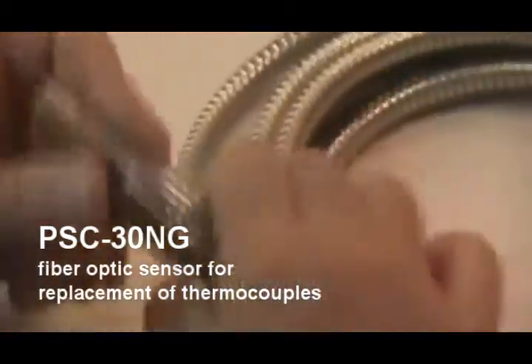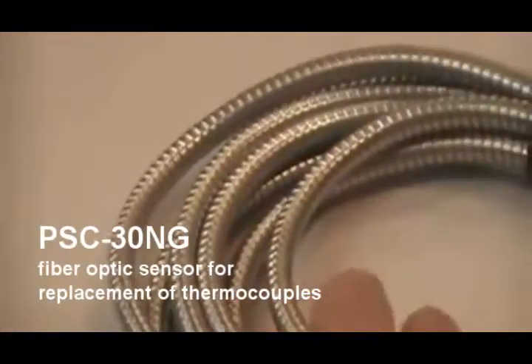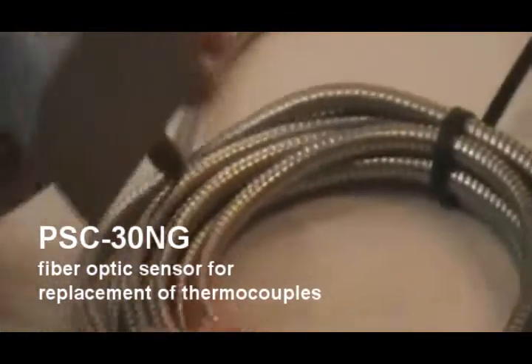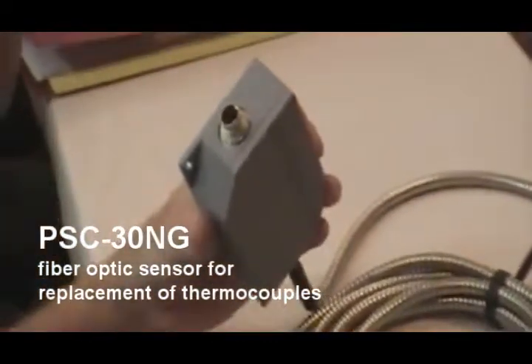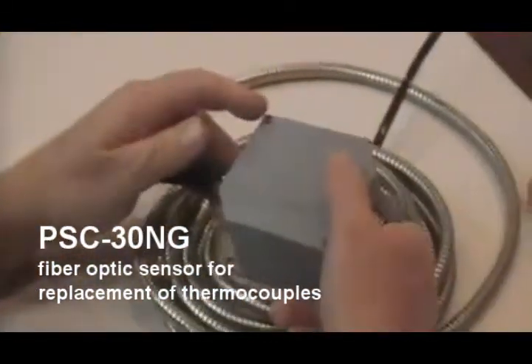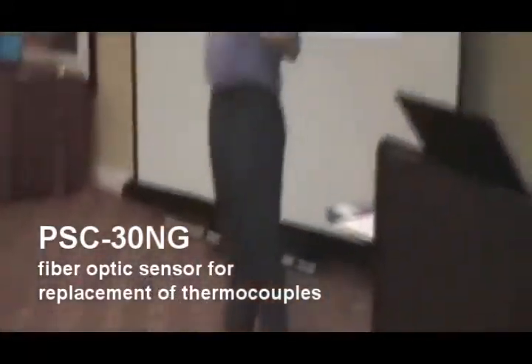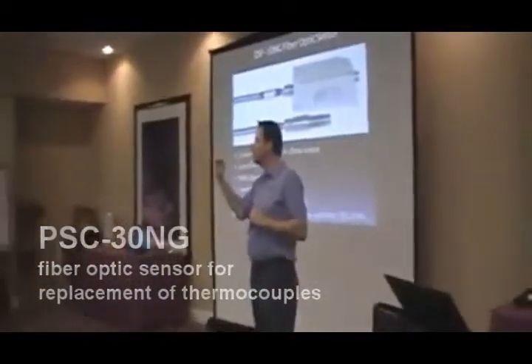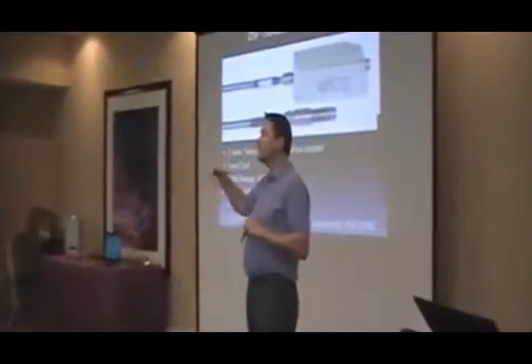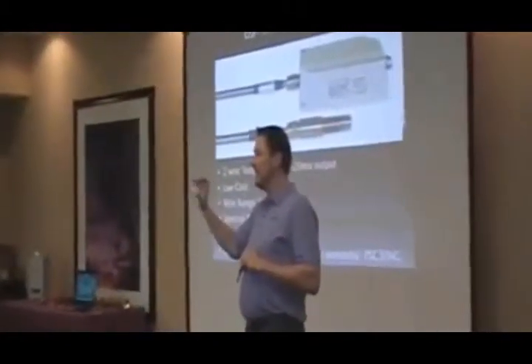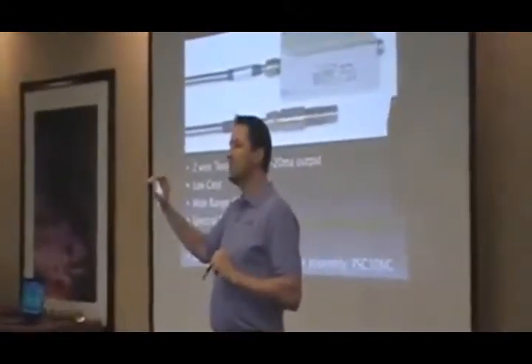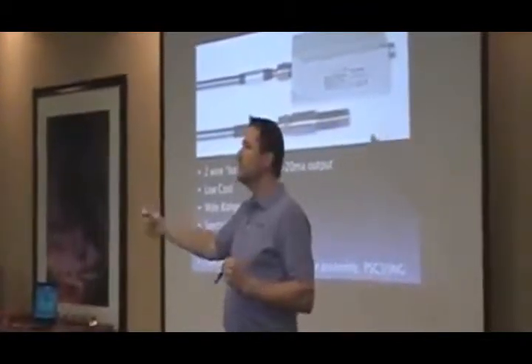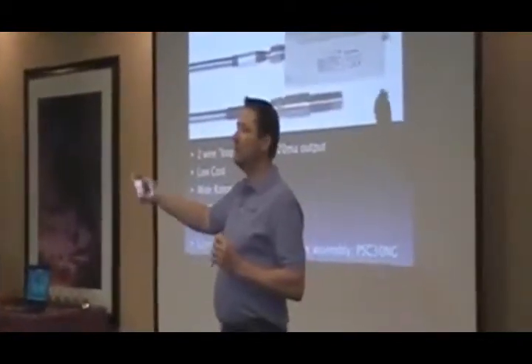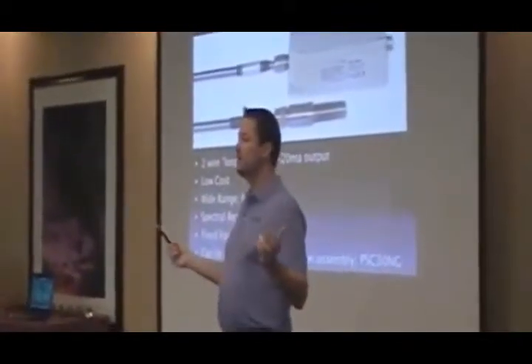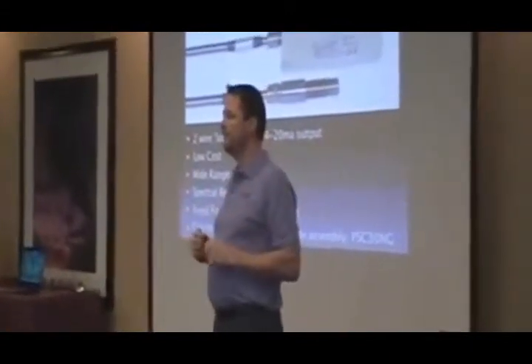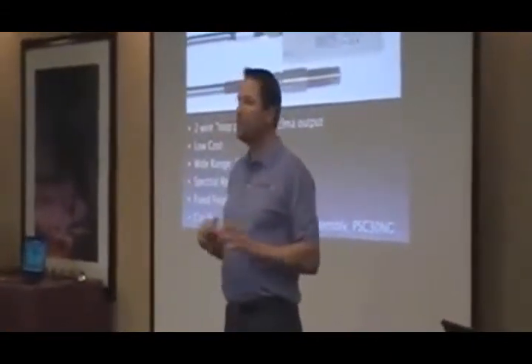Basically, what that does is adapt the lens to a target tube. Remember I mentioned earlier, if we look inside a crevice or a hole, your emissivity goes up. 3 foot, 5 foot, whatever target tube, but it's closed-ended at the end. I don't care if it's aluminum, the target tube. The reflections in the emission cannot escape. So you're capturing many more than 8 reflections. Your emissivity is going at 99%, almost 100%. So it doesn't matter what type of material.